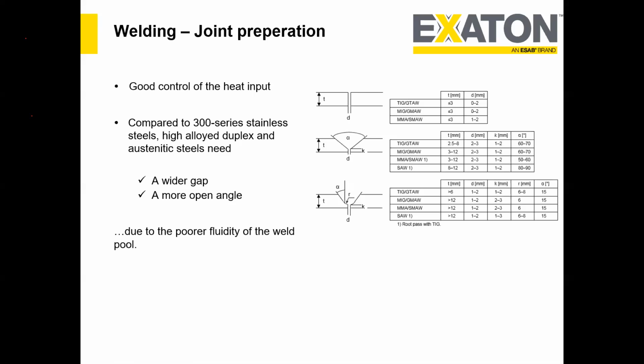So it will have a lower pitting resistance. At the same time, it will not have enough microstructural balance. So a wider root gap is important. Root face is also important. The root face gives more access for the welder to melt the filler metal, and the wider gap gives more access for the welder. So compared to stainless steel, we recommend a wider root gap, a root face, and a larger groove angle, for better access.